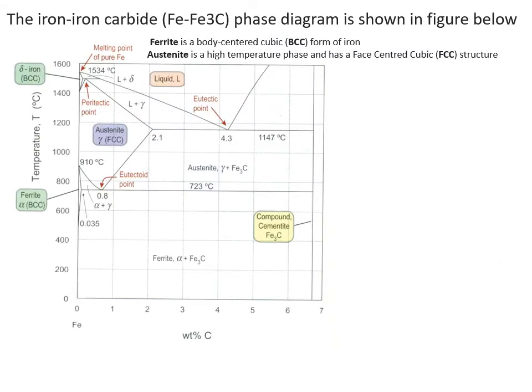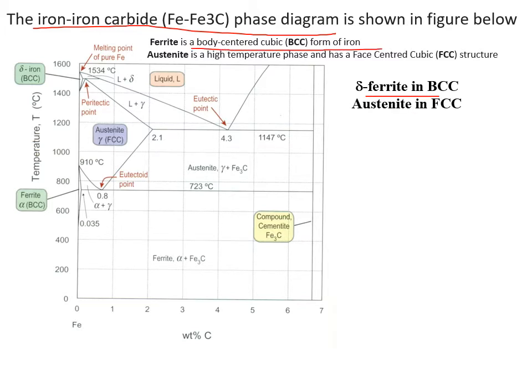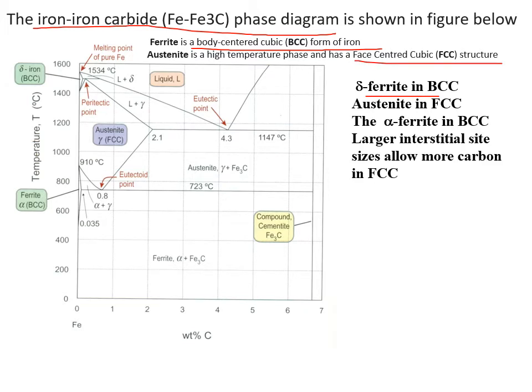So in this slide here, we're looking at an iron-iron carbide phase diagram. We're looking at ferrite, which is a BCC, or body-centered cubic, form of iron, and austenite, which is a face-centered cubic structure. The larger interstitial site allows for more carbon in our FCC, so up to 2.1% by weight, which we look back over here. Here's our 2.1% over here.